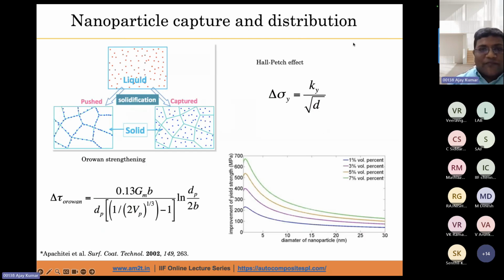Now let us discuss some fundamentals when we use the casting process, when we melt the material and solidify the material. So we have the microstructure where we have the grain boundaries, and then we are using the second phase particles. So either these second phase particles will be sitting on the grain boundaries, or they will be inside the grains. So intragranular or intergranular, these two types of things may happen depending on the manufacturing process. If we are able to refine the grains during this manufacturing process, then the strength of the MMC also will increase, and you can also see the grain size we can control in various ways. So we can use the grain boundary strengthening mechanism and Orowan strengthening mechanism to explain the MMC strengthening.